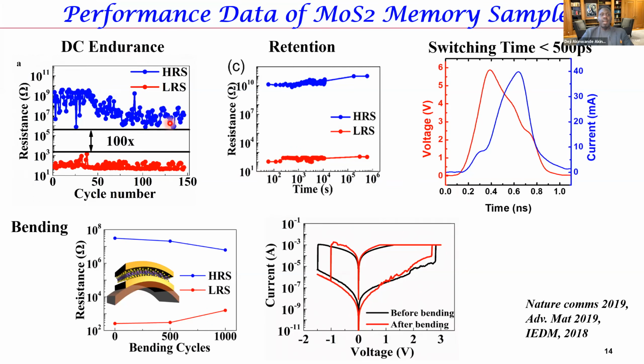We don't actually have the testing capability to do proper cycling tests, so these are DC endurance tests instead of the desirable pulse testing. Nonetheless, we can get hundreds of cycles, and this is very repeatable. Retention, as I mentioned, remains in that state at room temperature under ambient conditions.